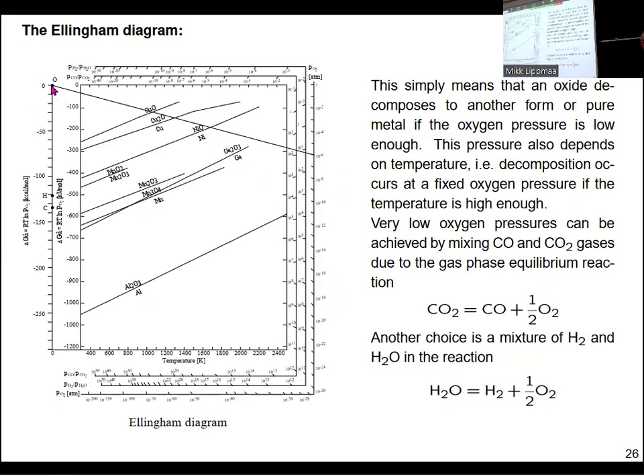And then you take from here a line. Let's say that we are at 10 to minus 6 atmosphere pressure. And you draw a line here from the 0 point to this pressure line. And now you can have temperature on the bottom. So you see here is a line for nickel oxide thermodynamic equilibrium balance. So at this crossing point here, if we are on this side of the line, we get nickel oxide. And if we are on this side of the line, we get nickel.